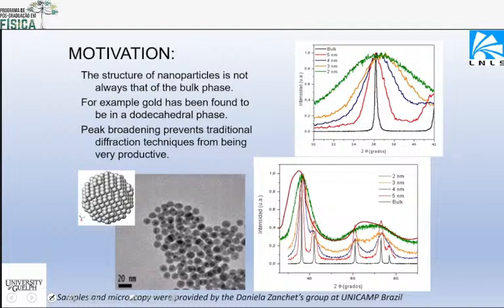So one of the most important things I want to teach you in this presentation is how we're going to get around this problem. At the time, people thought, well, you're not going to use X-ray diffraction to solve the structure of nanoparticles. You can't use it because the particle sizes are so small that you don't get good sharp diffraction. You need long-range order to get sharp peaks. The thing is that that's not true. X-ray diffraction can get you information, and excellent information, about even nanoparticles and even amorphous materials.